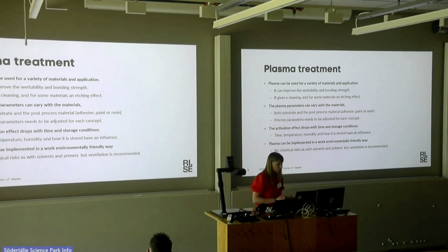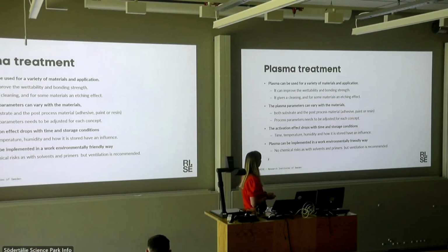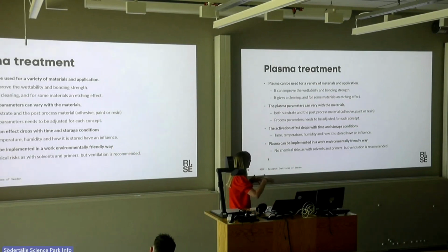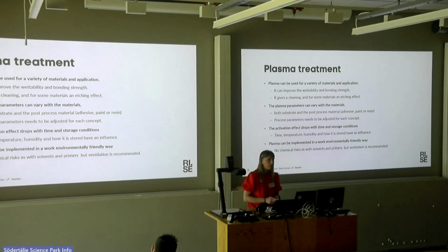Let's take this really quickly. What we have seen with plasma is that you can use it for a broad variety of materials and applications. It improves the wettability, bonding strength, and some cleaning effect also, but it's not so strong. You have the air pressure, so you can get rid of some particles if they are not too well bound to the surface. But it's not as powerful as a laser treatment, of course. You need to adjust the plasma parameters to your material, so you don't have exactly the same effect with polypropylene plastic as with PET, for example, or with metal.